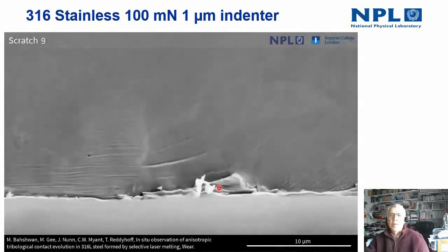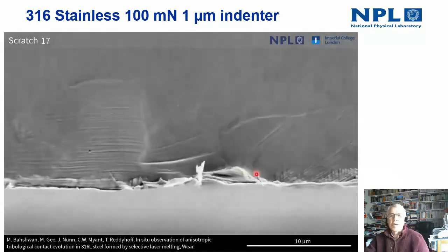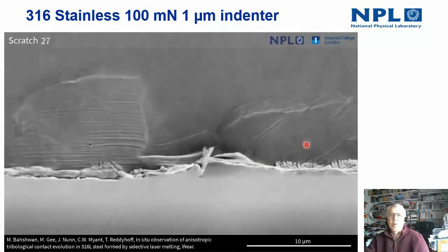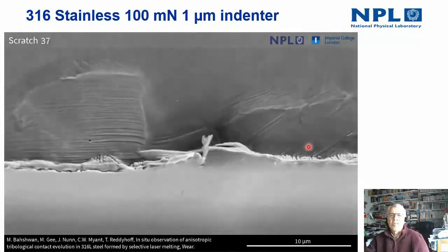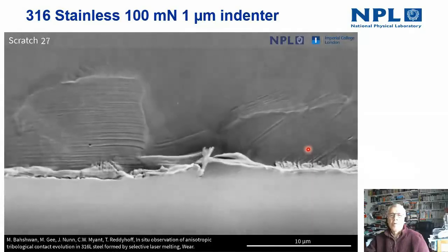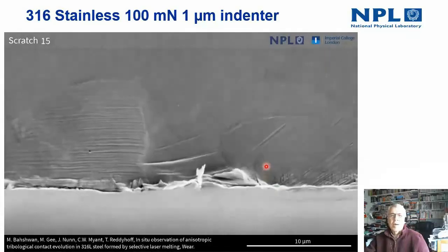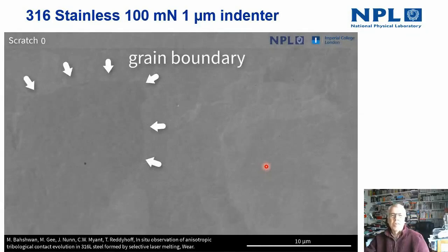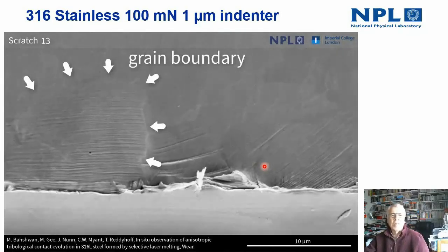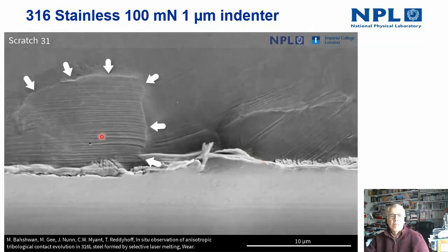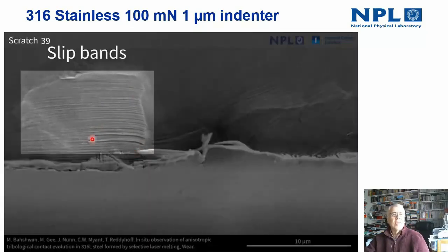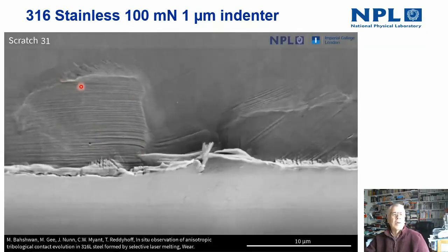And one of the features that interested me in particular here was just here you can just about see a crack forming in this grain. So severe damage and failure is beginning to occur here. This is just outlining where that slip area is.